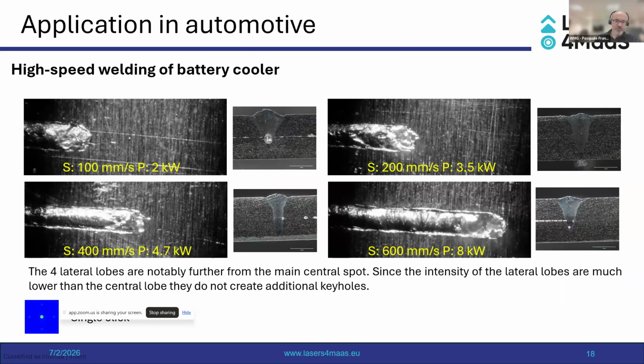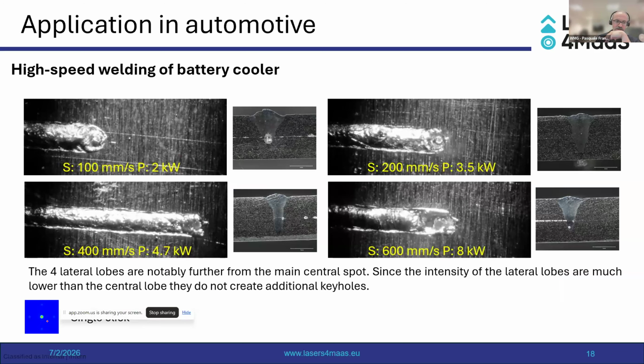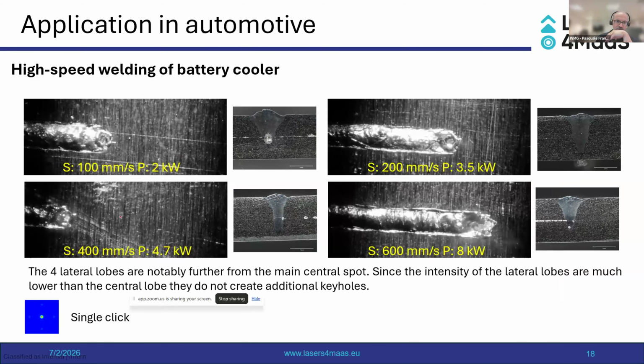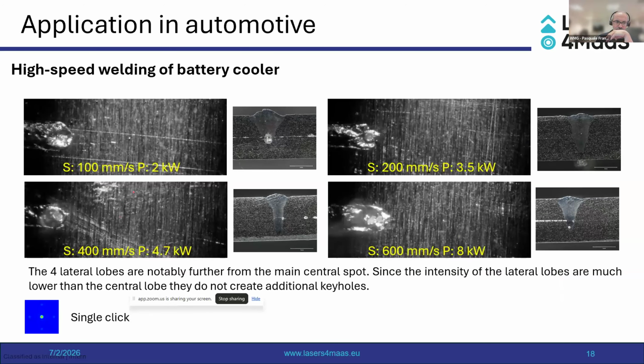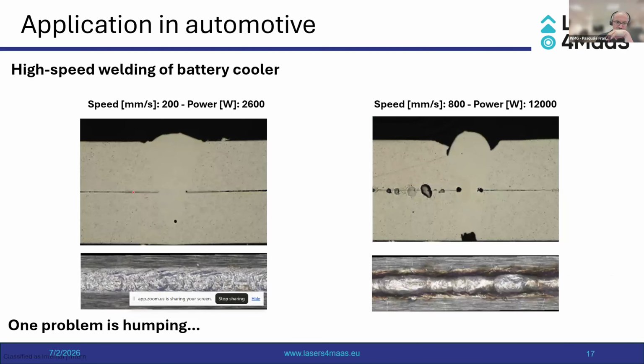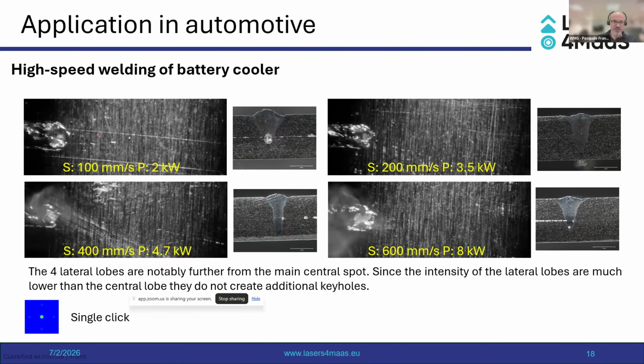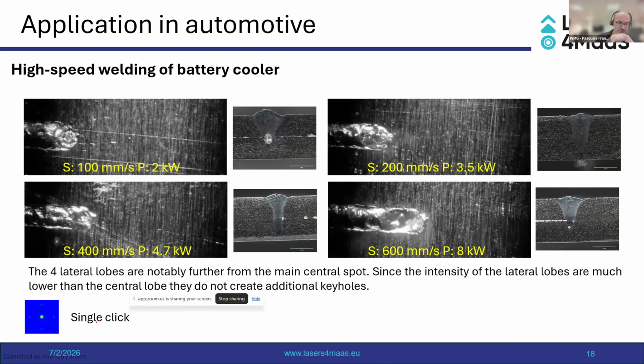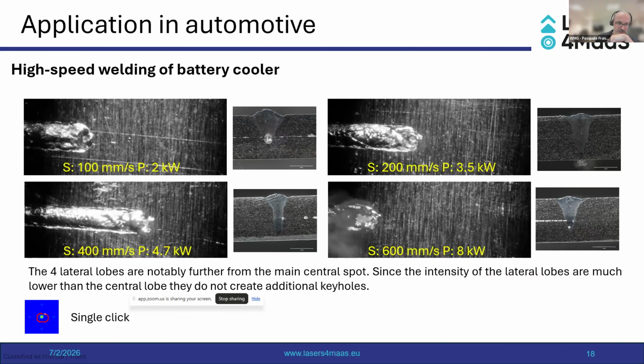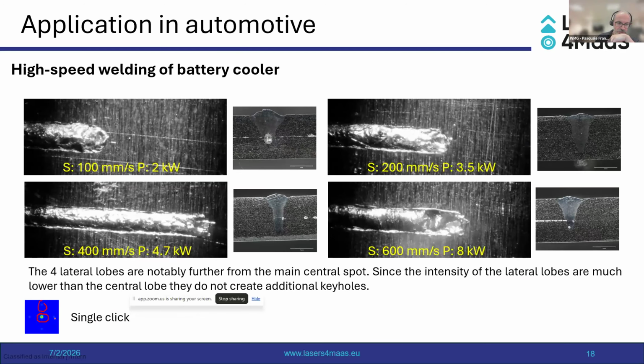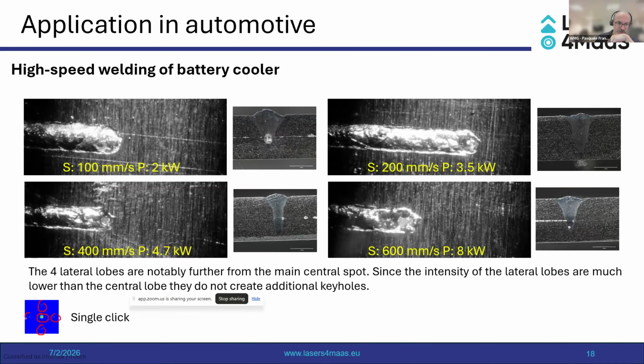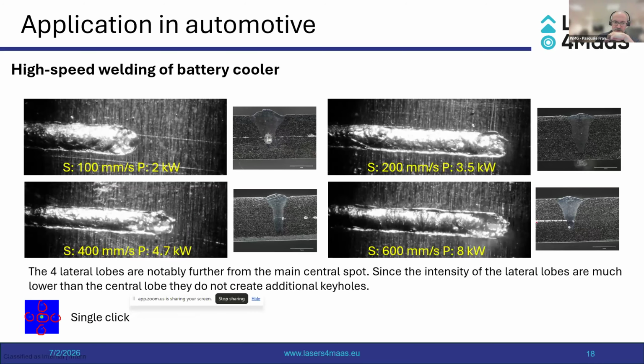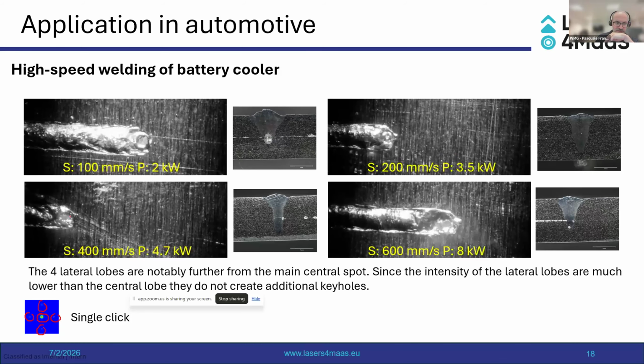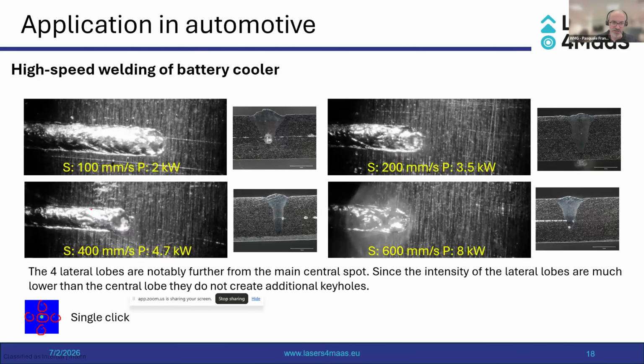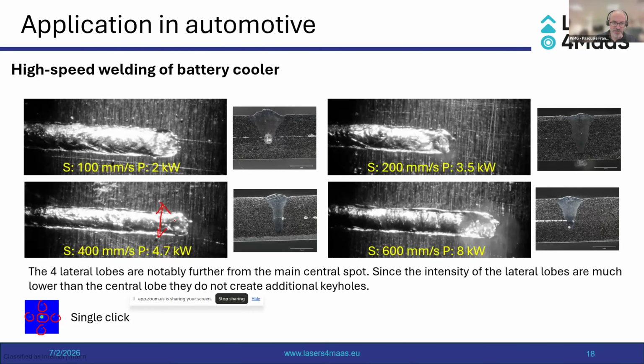We have done extensive testing using different beam shaping profiles. This one we call single click profile. Let me start the video again. Sorry, there is a delay. Yeah, so this shape we call single click. You basically have a central high intensity spot in the center, and then there are 4 small lobes on the sides. You can see what I'm marking now on the screen. Because of that, you get a pretty nice weld profile even at 600 millimeters per second. And you can literally see from the high-speed video the side lobes that are making the molten pool a bit wider in the transversal direction, and this is helping in reducing the high-speed jet from the molten pool.